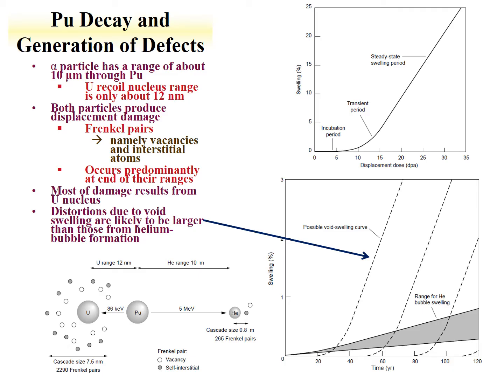Generally speaking, this swelling behavior has three main components as a function of dose. The dose is described in DPA — displacements per atom — representing how many times an atom in the lattice gets displaced. There's an incubation period where some dose effect occurs and no swelling is evident; a transient period where we have higher dose and swelling increases; then a steady state where there's a relationship between dose and swelling. The actual swelling as a function of DPA varies with materials and conditions.